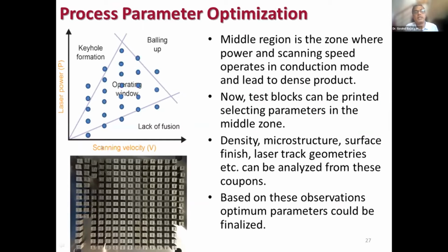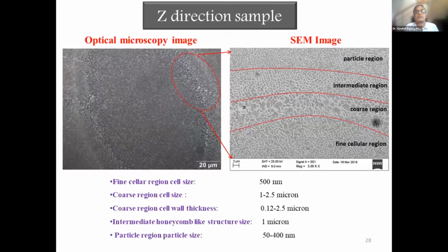We go for printing cubes in this prism. And based on the detailed study of the density and the microstructure, we arrive at optimized parameters. Just to show the microstructure we obtained in AlSi10Mg, it is interesting to see that we have a heat affected zone. This fine cellular zone is the melt pool zone, and the nearby zone is the heat affected zone in the previous solid layer.